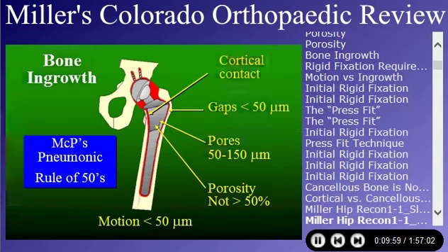in those areas. So I've thrown a lot at you. One little mnemonic that's helped us for the test is the mnemonic rule of 50s. First of all, you want cortical contact, but if you just remember the 50s rules, it'll get you in the ballpark. You want to keep your gaps less than 50 microns. You want your pores between 50 and 150 microns. You want your porosity not to be greater than 50%. And you want your micromotion less than 50 microns. And they'll give you some ranges, but if you just try to remember that, McPherson's 50s, that'll kind of get you there, okay?